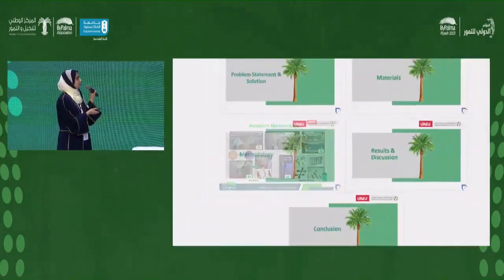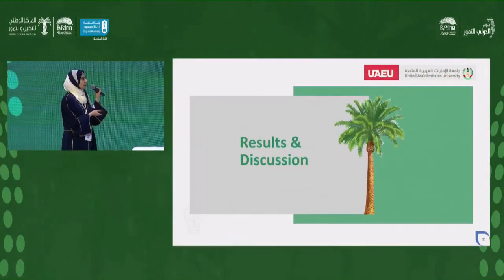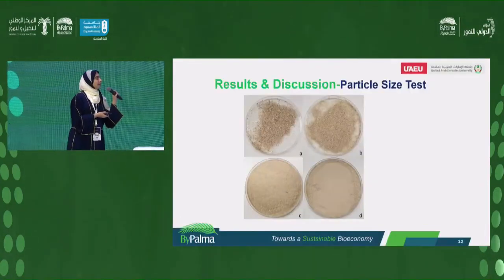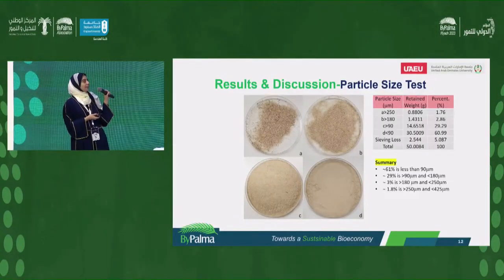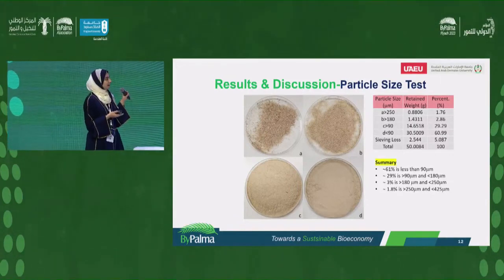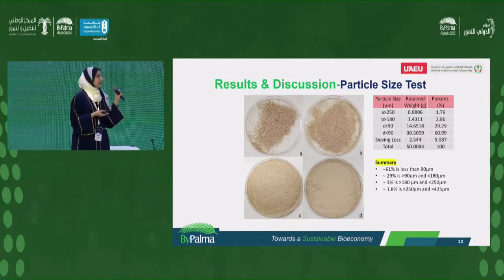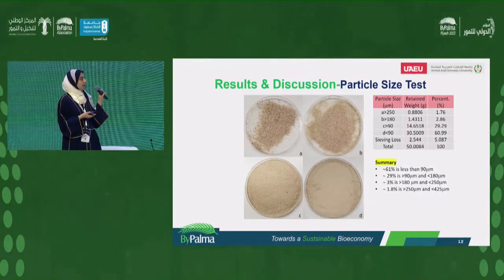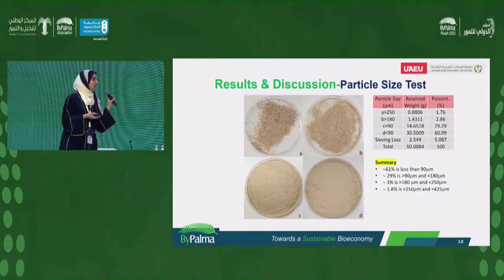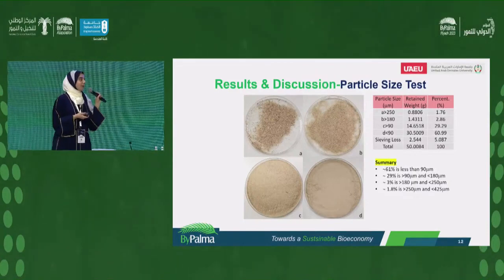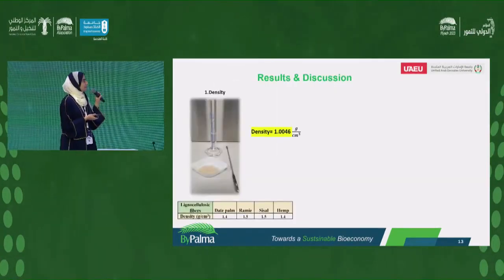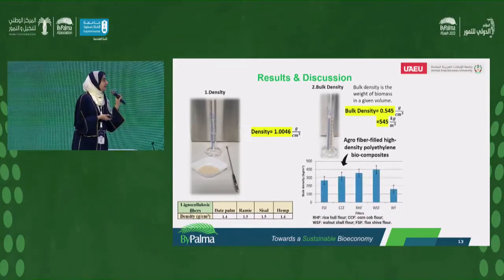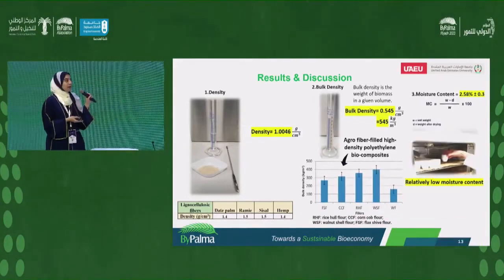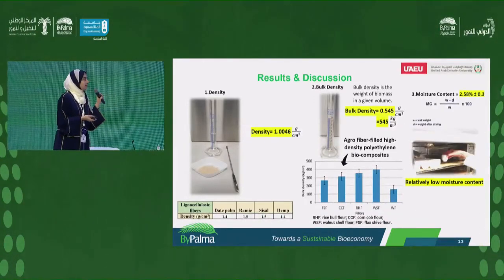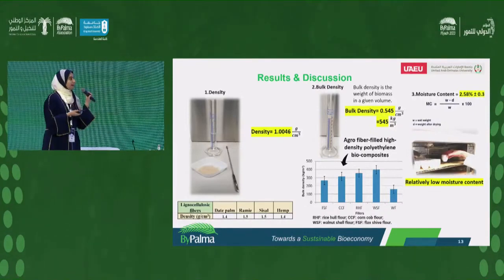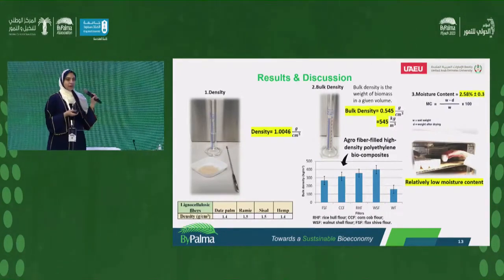Moving to the results and discussion, as we can see, we started with the particle size distribution test, and we can see that 61% after grinding is less than 90 microns, and we have only 1.8% between 250 and 425 microns. The density and the bulk density and moisture content were also tested, and we found it is acceptable and comparable with other fibers available, and the moisture content is relatively low, which is good.